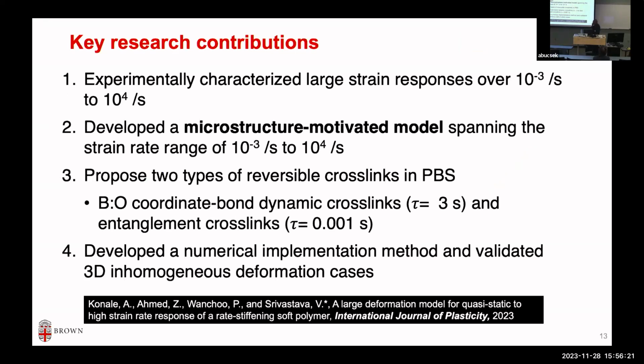So what are the key contributions, right? We have done characterization over a wide range, 10 to the power minus 3 to 10 to the power 4 per second, of these materials that are of interest for large strain. We have developed a microstructure motivated model. I'll describe the model in a little bit, but we found that in addition to boron oxygen coordinate bond dynamics, there's also additional entanglement dynamic cross-linking. The order of millisecond is needed. We also developed the numerical implementation that we've skipped. I'm not going to talk about it, but you can find that information in the paper.